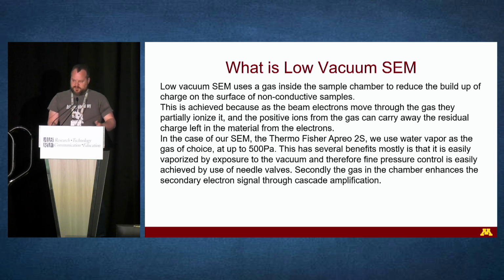This has two effects. One, as the primary electron beam enters the chamber, it scatters off some of the gas molecules, ionizes them, and those positive ions can then recombine with the electrons stuck to the surface and carry the charge away. But also, you get a boost of the signal. As the secondary electrons exit the material, they can hit other gas molecules, generate more electrons, and you get a cascade amplification of the signal.